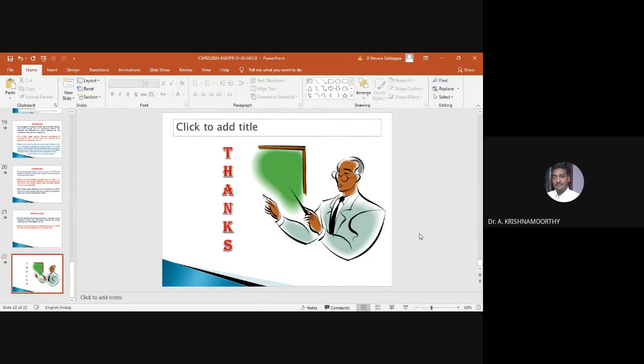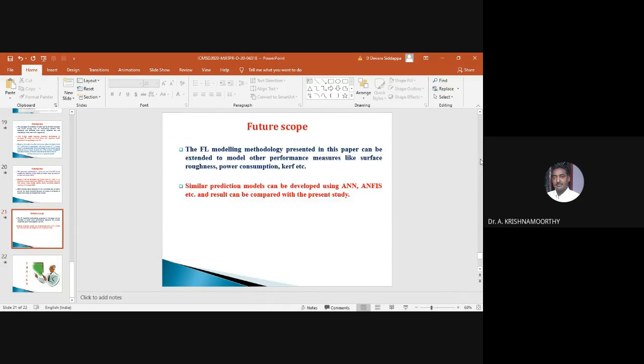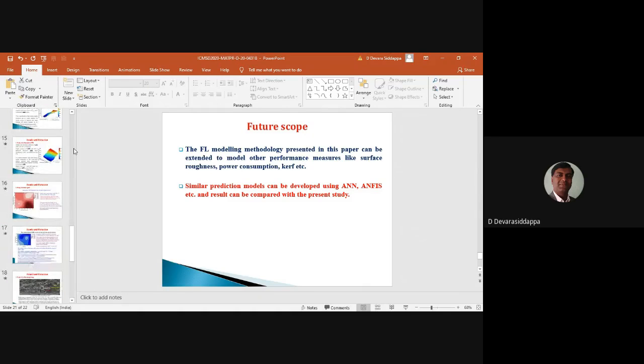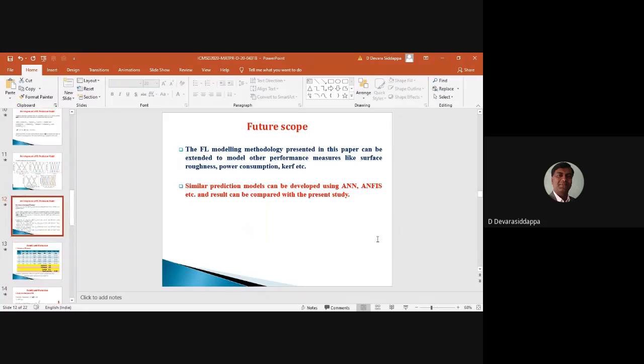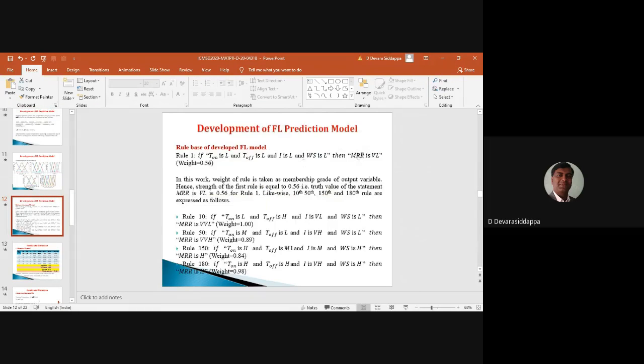Then the weight, based on your experience, you allotted 0.56? Actually, weight is by default 1 in most cases; researchers take it as 1. But what I did here, sir, instead of assigning weight equal to 1, was to take the membership grade of the output variable as the weight. In different cases, the weight value varies. Like in the first case, the membership grade of MRR in the very low fuzzy set is 0.56, and the same is taken. In rule 10, the weight is coming as 1, and for rule 180 the weight is coming as 0.8. So that is the logic behind taking this weight, sir. Okay.